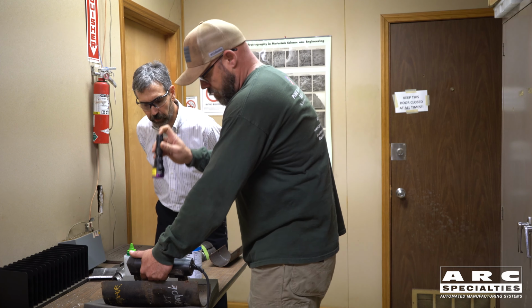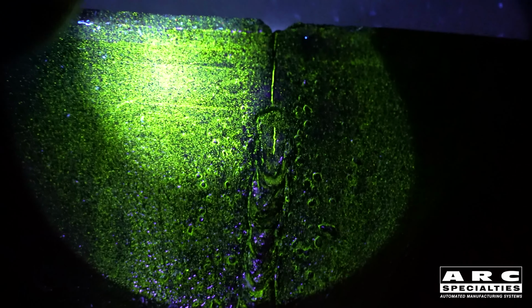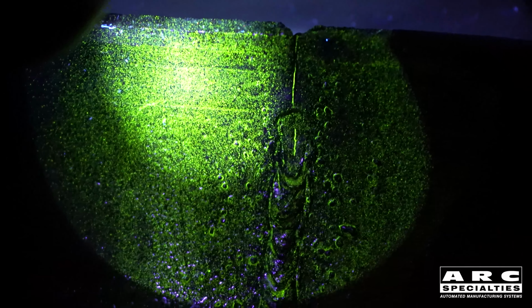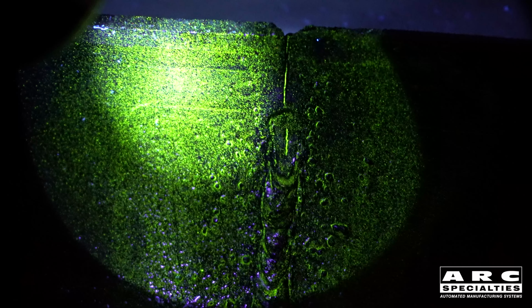So what do you got? You got a good part? No, it's not. So I see a crack on the center line. What is that? A crater crack? It's a crater crack. It's probably due to the lack of fusion. The lack of fusion created a stress riser and created the crater crack.